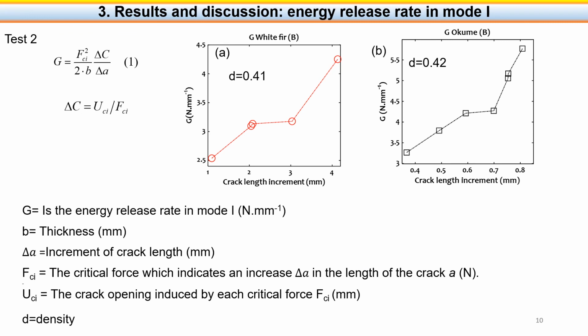This figure shows the evolution of the energy restitution rate with the crack increment for the species. The amount of initial energy required for crack propagation in Okume is slightly higher than that of white fir. This can be justified by the density of the two specimens tested, which are 0.42 for the Okume and 0.41 for the white fir. This seems to confirm the observation of Odunga and Hall on the effect of density on the rate of energy restitution, where we note that the rate of energy restitution of the denser species was higher than that of the less dense species.